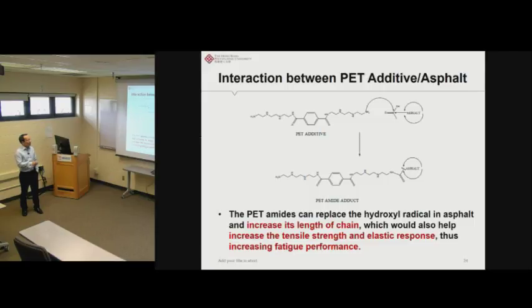But after we add the PET additive, we introduce the additive into the asphalt binder. Such a replacement increases the length of the chain of the binder, which could help to increase the tensile strength and the elastic response of the asphalt binder material. Because of this, the fatigue performance of the binder is expected to be increased. So this is the potential reason why the PET additive can significantly help to improve the fatigue performance of the binder.